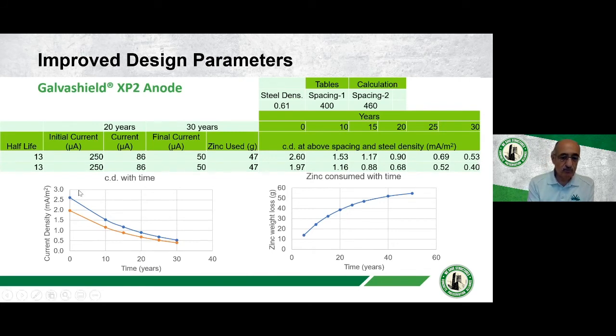And that's this top blue line. That's the current distribution as it diminishes with time. We also have a graph here for zinc consumption. So for 30 years, we've consumed almost 50 grams of zinc, or we will be. And the type of anode that we've chosen has significantly more than that amount of zinc. So we're okay on that front as well.